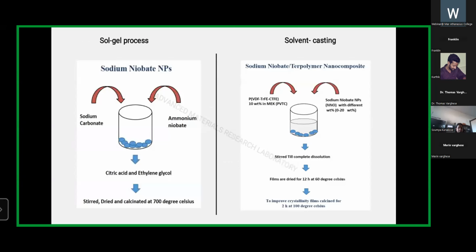Coming to the synthesis method, sodium niobate nanoparticles are prepared by the sol gel process. Here the stoichiometric amounts of sodium carbonate and ammonium niobate are selected. Citric acid is used as a chelating agent, and ethylene glycol is used as a stabilizing agent. Finally, the solution is stirred, dried, and calcinated at 700 degrees Celsius to obtain the pure phase.